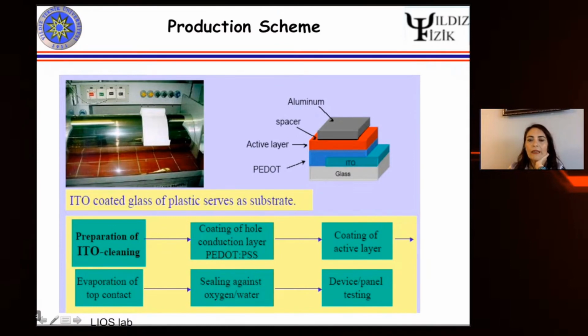We have the glass or the PET substrate. It depends on the flexibility you require. If you do not want a flexible substrate, then you can use glass. And then ITO is coated. Part of the ITO is etched, and on top of it, we have the PEDOT layer. And we have the active layer in which electron donating and electron accepting materials are blended together. And we have a spacer here and aluminum as an electrode.